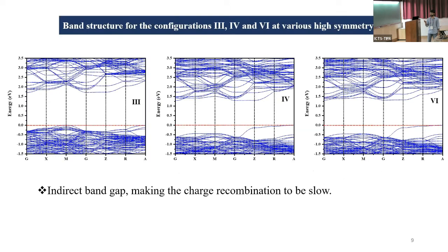Now to find the nature of the band gap, whether it is direct or indirect, we calculated the band structure for configuration 3, 4, and 6 along the various high symmetry points. But we found that the nature of the band gap is indeed indirect, having valence band maxima at A point and conduction band minima at gamma point in all the configurations.